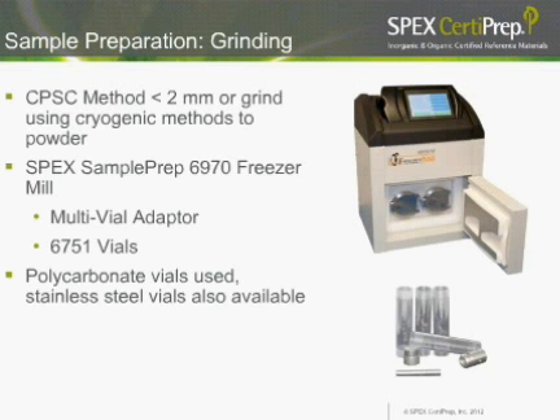For us, since we work with our sister company, Spex Sample Prep, it was a no-brainer for us. We decided that we were going to grind this sample. So in the Consumer Product Safety Commission method, it does suggest that you reduce the sample size to below 2 millimeter samples, or you grind it using a cryogenic type of method. For us, we use the Spex Sample Prep freezer mill, the 6970 freezer mill. We had an adapter which allowed us to do multiple vials at one time, so it increased our throughput of these toys very quickly.